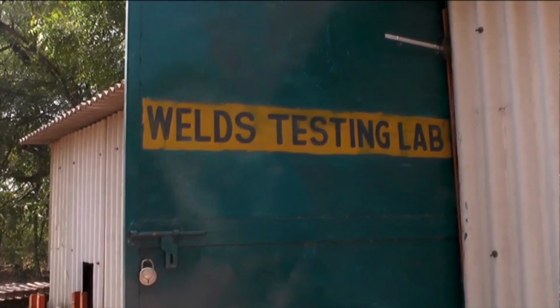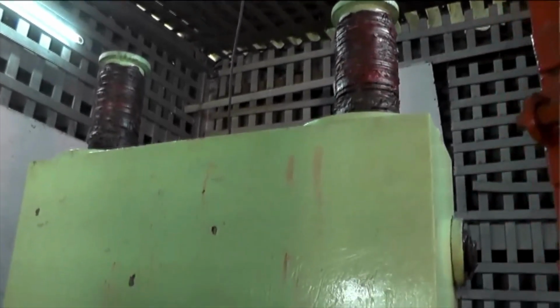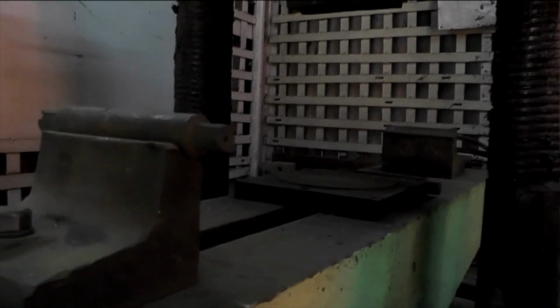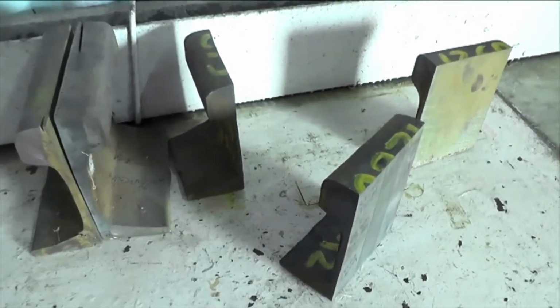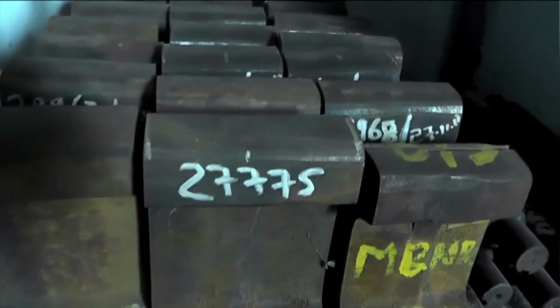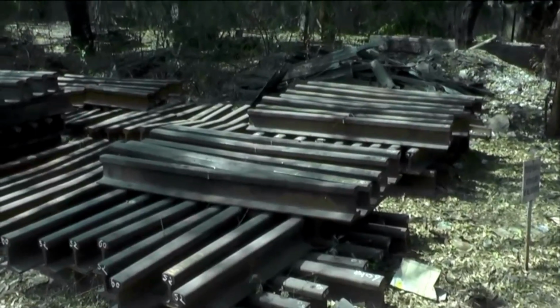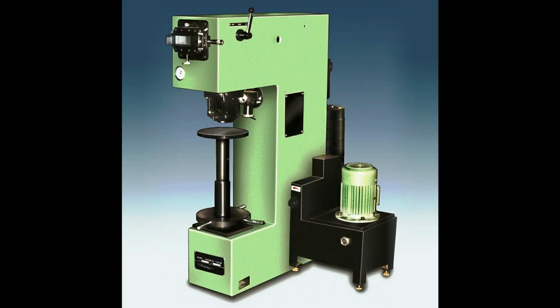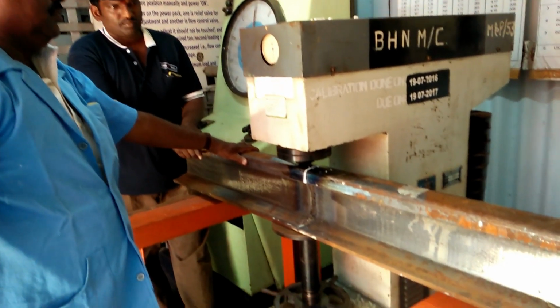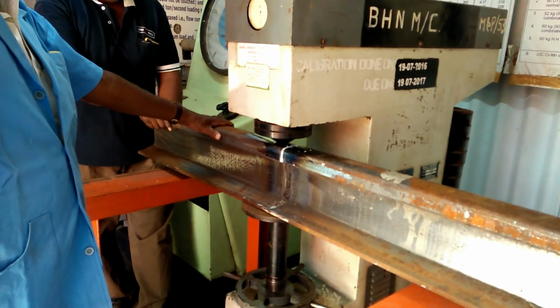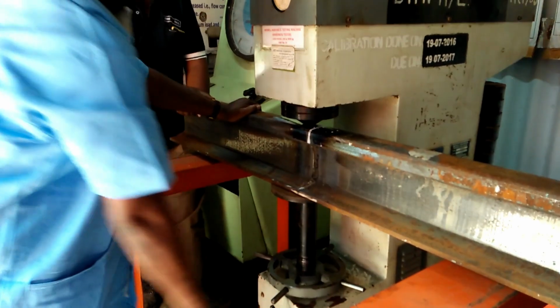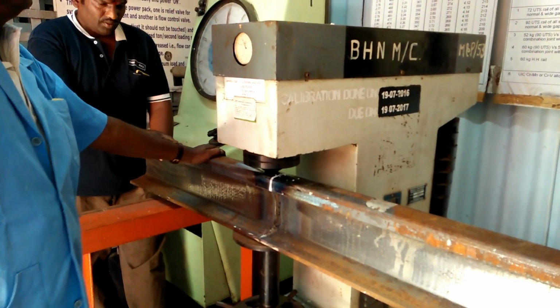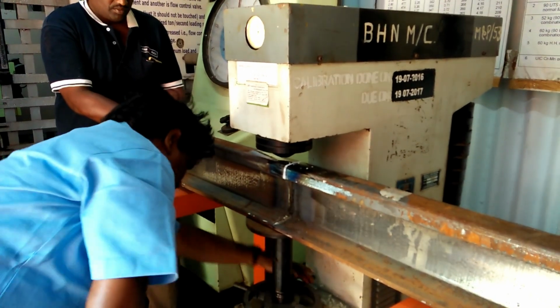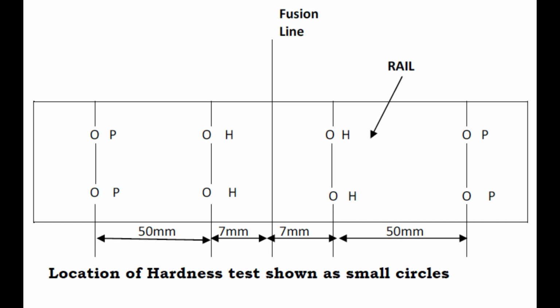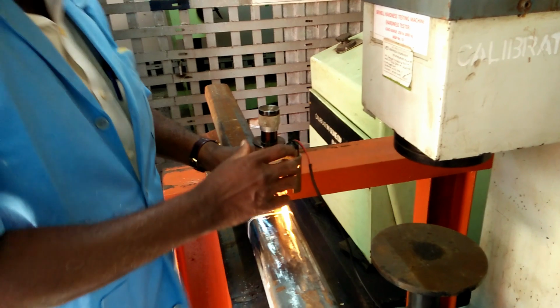Destructive tests means testing the part, or here it is the rail weld. That's why for destructive tests we have a frequency. NDT tests we must do with 100% checking. Destructive tests are the Brinell hardness test, then transverse load test, macro examination and micro examination. This Brinell hardness testing machine's capacity is 3000 kgs. The hardness test is to know the hardness of the parent metal, that is the rail material, as well as the heat affected zone of the rail weld, and shall be conducted on the test weld sample before conducting the transverse load test.